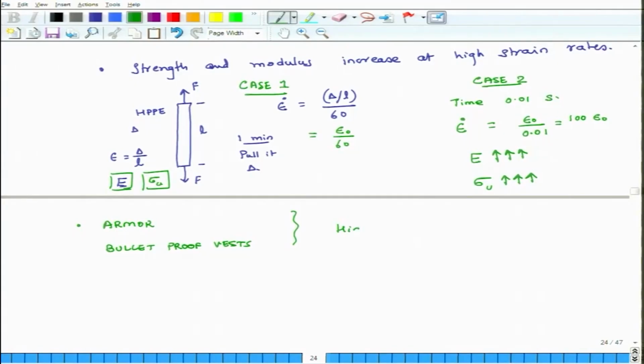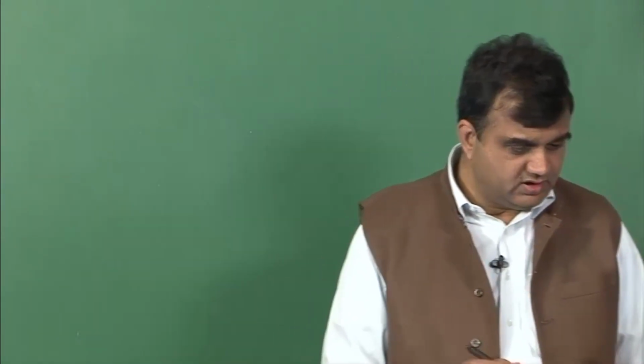So, these are very efficient materials for these kinds of high strain rate applications, and they are more advanced and they have less density. Kevlar is also good for high strain rate applications, but what is Kevlar's density? We saw it earlier. It is about 1.4 or 1.5. These are lighter than Kevlar, they are less than water, so they are less than 1. So, with even less material you get similar benefits to what Kevlar gives you. For that reason these materials are very useful.